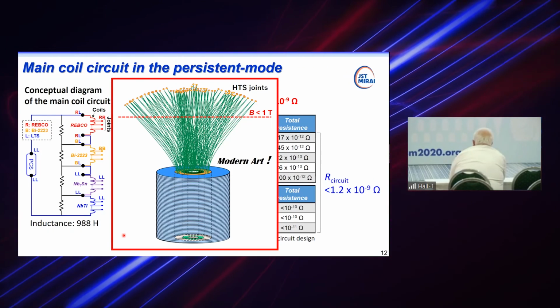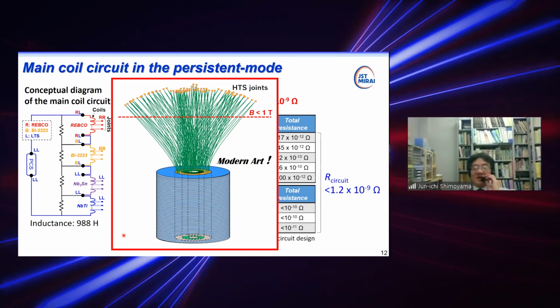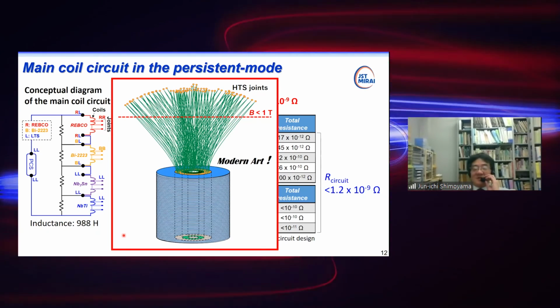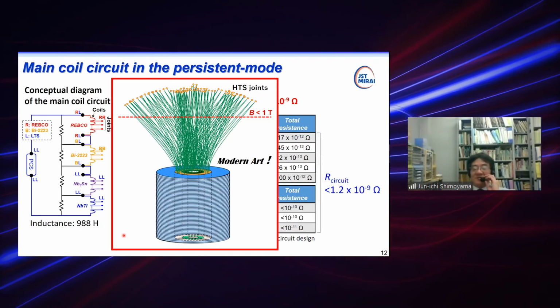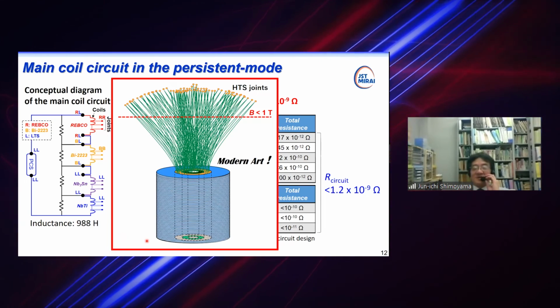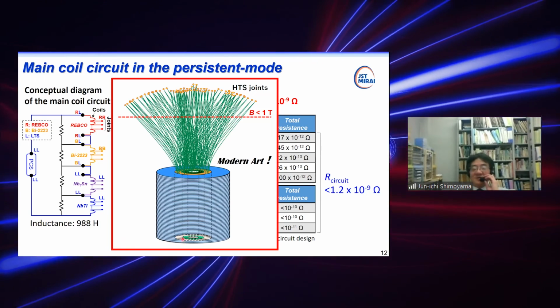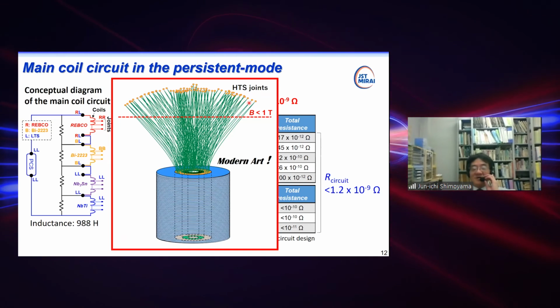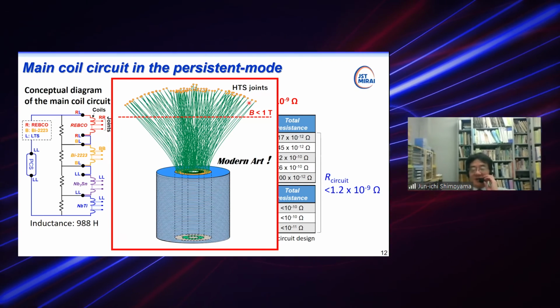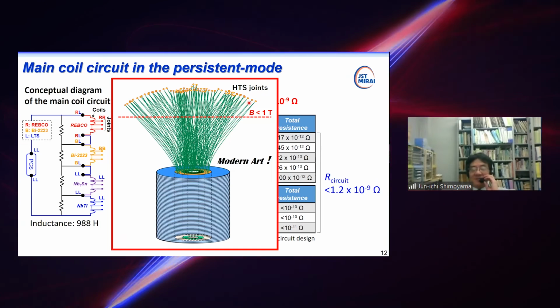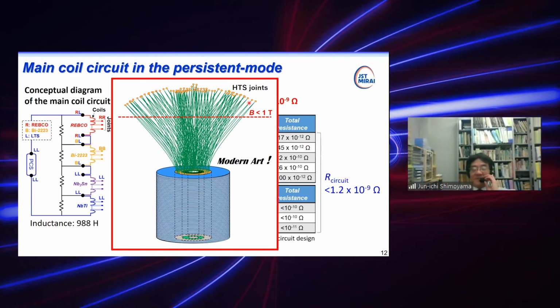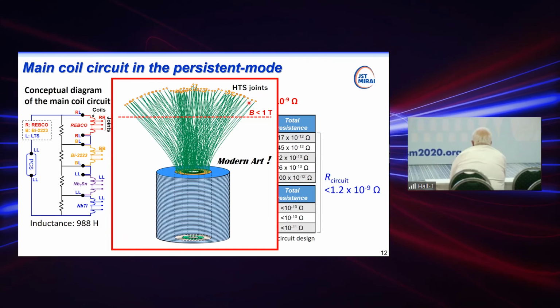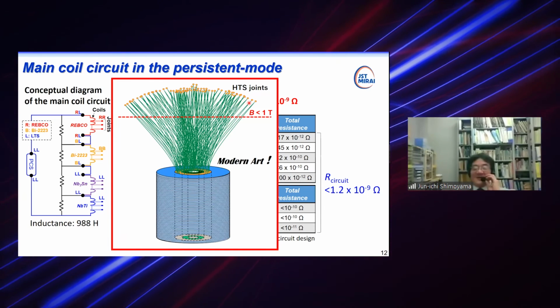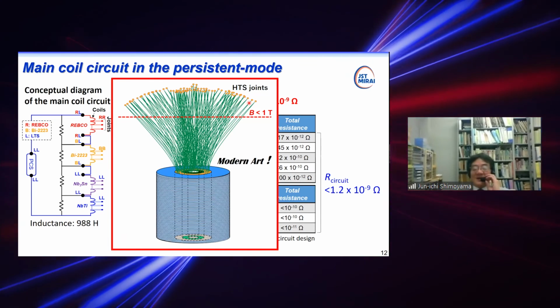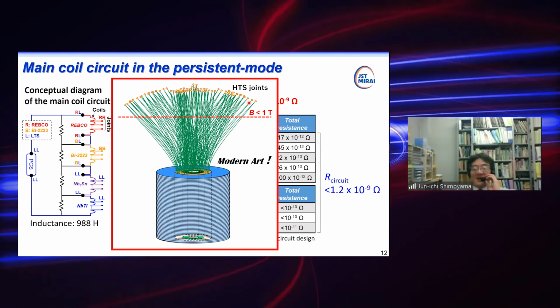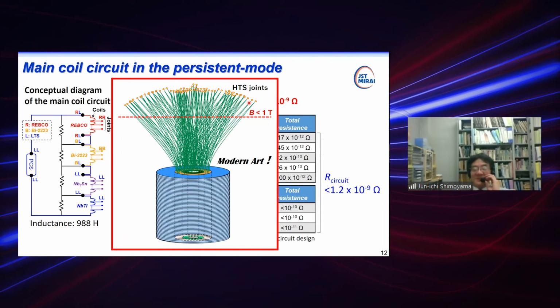And we can use the magnetic shielding technique. So we can reduce the magnetic field down to 0.2 Tesla or something like that. In this case, we can use these joints at higher temperatures, 20 Kelvin, 40 Kelvin, and even at 77 Kelvin, I believe. So did you try at 77 Kelvin liquid nitrogen temperature? Yeah, I want to try, but it's not scheduled in our program.